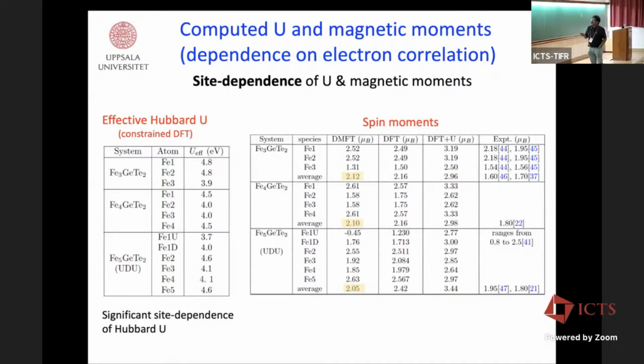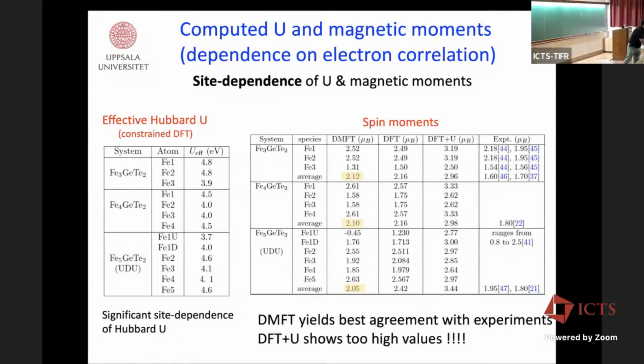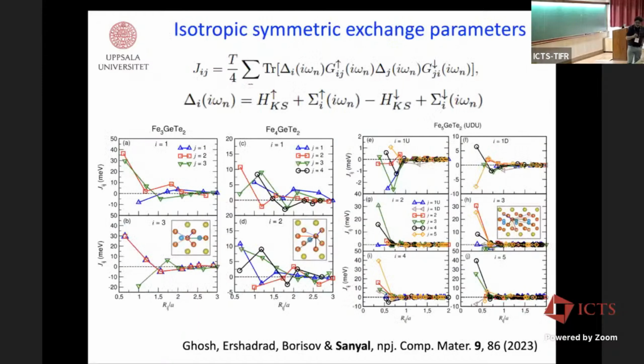Then Fe4GeTe2 also has a similar picture. Fe5GeTe2 is also the same: you see that DFT plus U always gives a very large estimation of the spin moments. Not only that, if you calculate the geometry, the geometrical parameters also come out to be inaccurate compared to the experimentally reported geometries. So that's why we can say that DFT plus U is not the choice of method for these metallic ferromagnets.